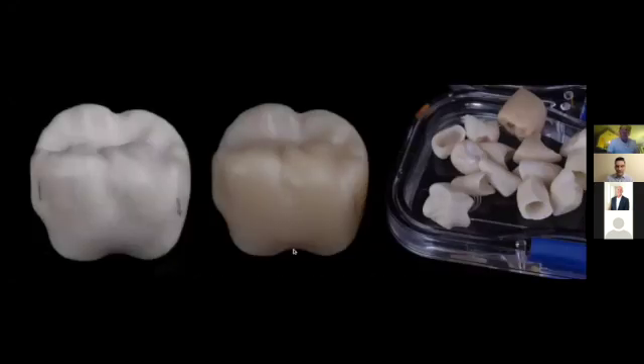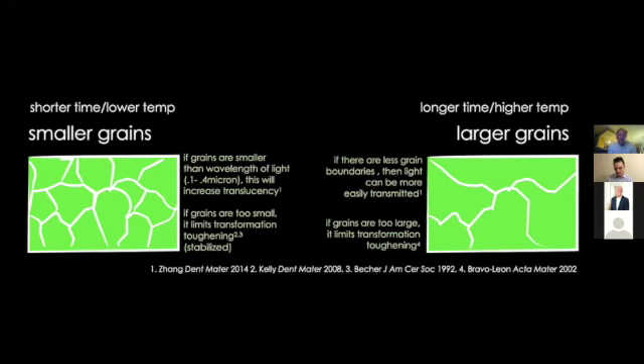Why don't you just mention, some people may have no idea what the sintering time is. It can be 1.5 to 8 hours, right? Yeah. When we talk about translucency of zirconia, we could talk about when BruxZir came out, that was supposed to be translucent zirconia, and then the anteriors, those are more translucent. Same thing with fast firing zirconia. I remember talking about fast firing, and to me that meant like 20 minutes. But then there are some people that talk about 1 hour firing as a fast fire, because it's 1 hour as compared to 8 hours. So yeah, I know that the times can vary a lot.